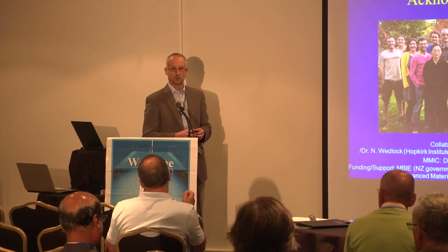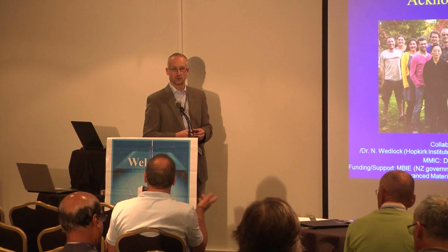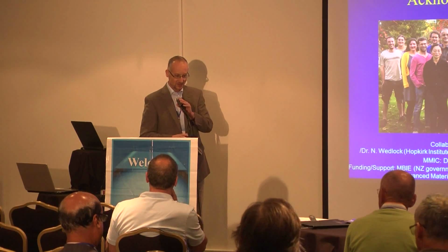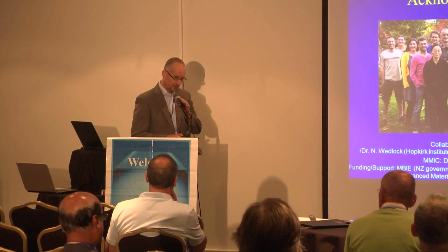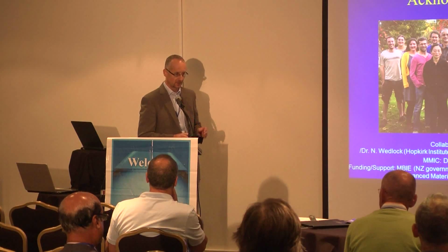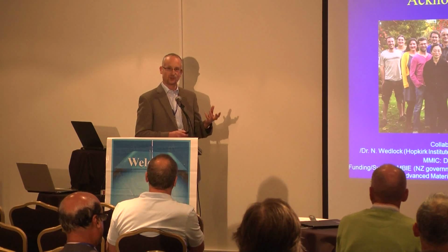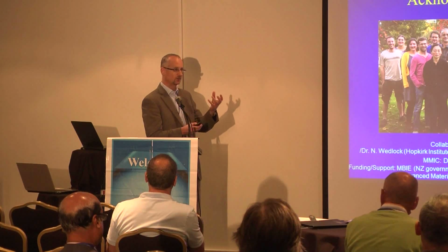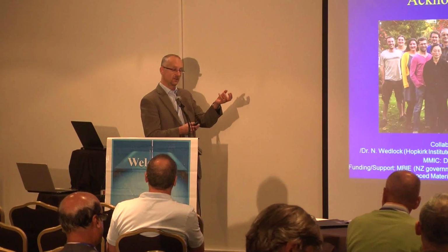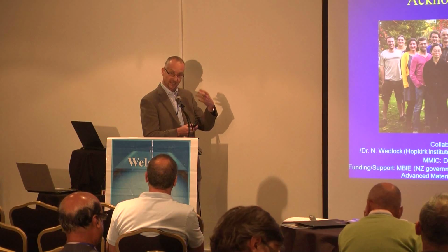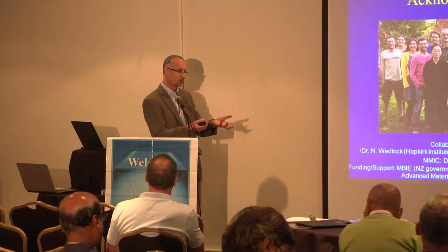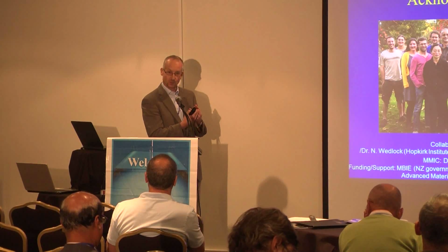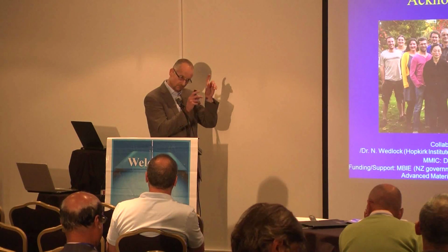Now, if you want to separate your protein, is there a way to clean the protein from the synthase? Yes. We did that as well. We published that, but we are still working on that possibility because it is actually a protein production system as well. It's not only displaying antigens, but you can also produce antigens by having self-cleavable tags, like inteins. You lower the pH, and then all of a sudden the proteins release, because we can obtain those polyester particles easily.